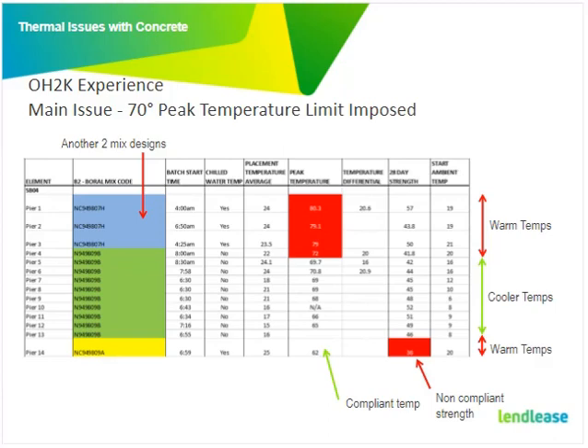The only time we managed to achieve the peak temperature limits was when it got to the winter months. Again, another 2 mix designs. We couldn't achieve it in the warmer months. It was only achievable in the cooler temps. But going back to this mix here, we dumped a whole lot of slag into the mix.